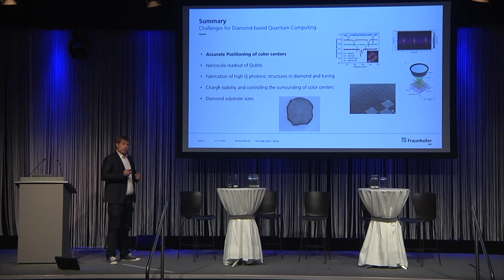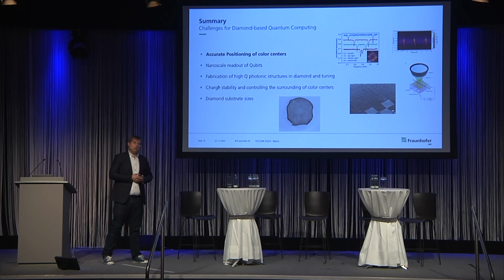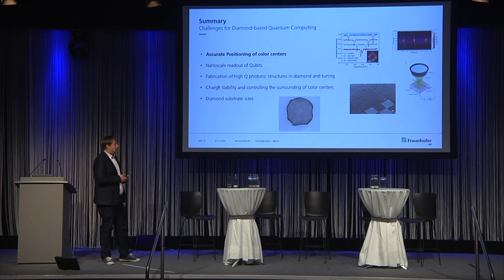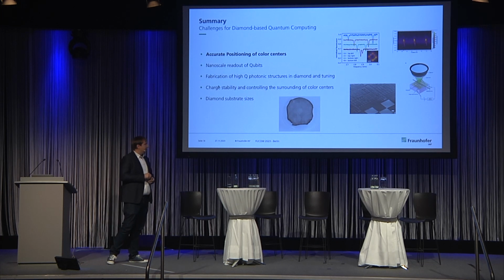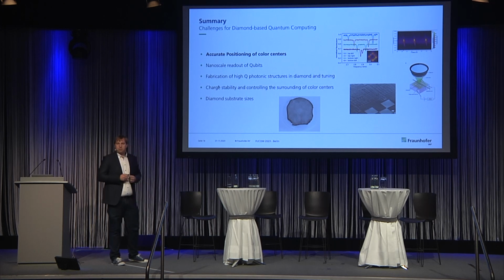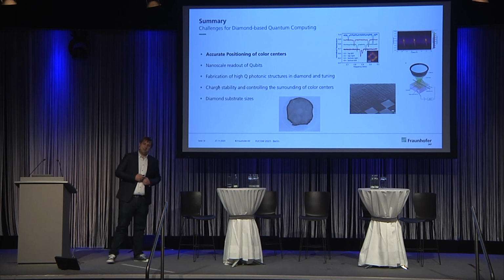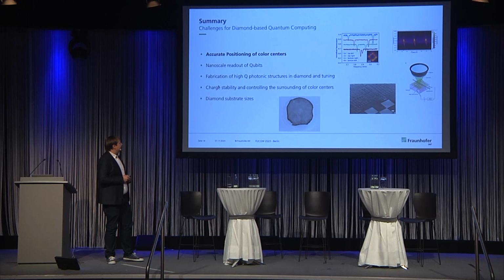One other thing is the readout that I mentioned briefly. Fabrication of these high Q photonic structures has been shown, but still needs some testing and probably will benefit from larger diamond substrate sizes. So this is a 2-inch wafer that was fabricated. It's not that nicely shaped as a silicon wafer, but it is possible to get to wafer size diamond. There are some drawbacks, but we can discuss these maybe at a later stage if you want.